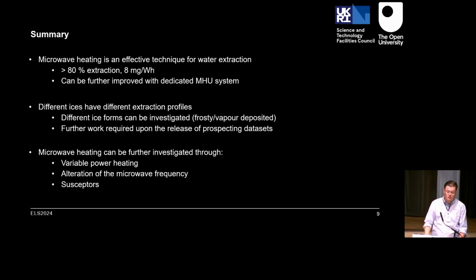So in summary, and a summary also of what I found out throughout my PhD, is that microwave heating is an effective technique for water extraction, even though microwave heating shouldn't be as good at lower temperatures. It seems it can produce a lot of water. And I think it could be further improved with a dedicated system for this. At the moment we are using a sintering system. I believe a more open cavity would be better rather than a standing wave configuration. We found that different ices have different extraction profiles, maybe not entirely surprising, and we need to do some further work on analyzing why this is occurring. But the good thing is that the extraction is high for all of them, really.